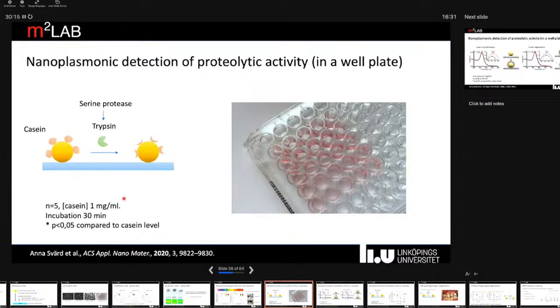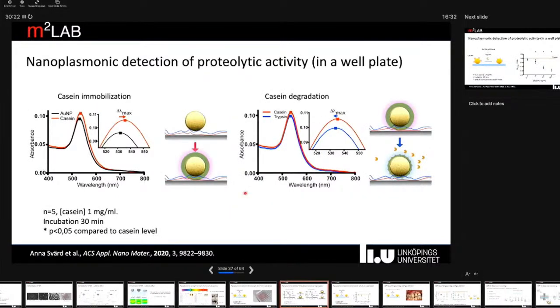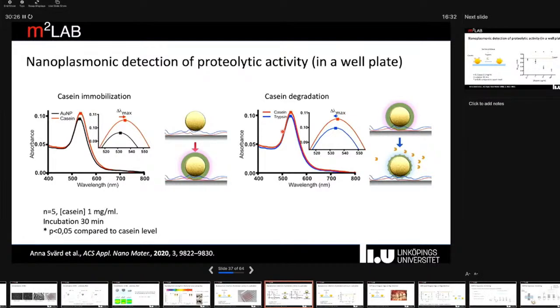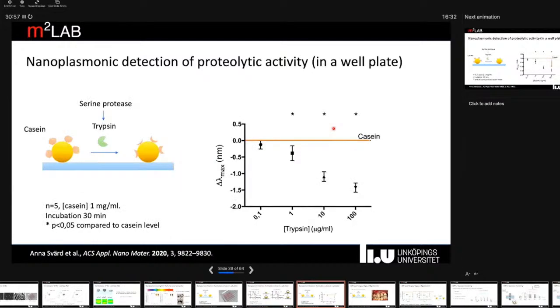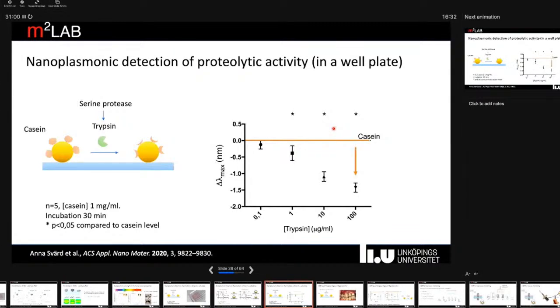So a very simple setup, and then exposing these sensors to trypsin, we can see that we get a blue shift of the plasmon band. So this shows the LSPR band during the casein immobilization or functionalization of the particles with casein. We have a red shift, and when we degrade the casein, we remove mass from the surface, which we see as a slight change in the LSPR band and intensity, but sufficiently large to see this quite clearly with a plate reader. And using this simple strategy, we can detect fairly low concentrations of trypsin. But it was not trypsin that was our main target in this case.